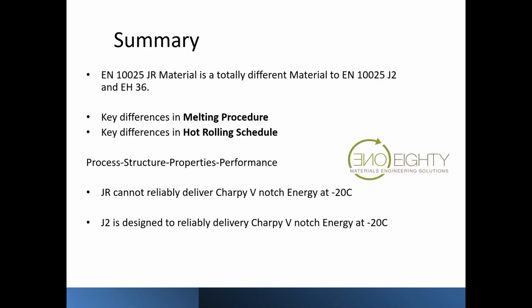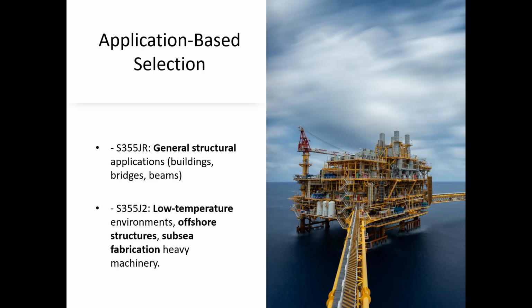So in summary, JR material is a totally different material to J2 and EH36. The key differences are in the melting procedure and the hot rolling schedule. This ties together with process, structure, properties, and performance. JR cannot reliably deliver on Charpy V-notch energy at -20. If you have a test result that gives you that, you were really lucky. But how many times has it failed 5 times before you got a result that passed? J2 is designed to be reliable and deliver Charpy V-notch energy at -20.